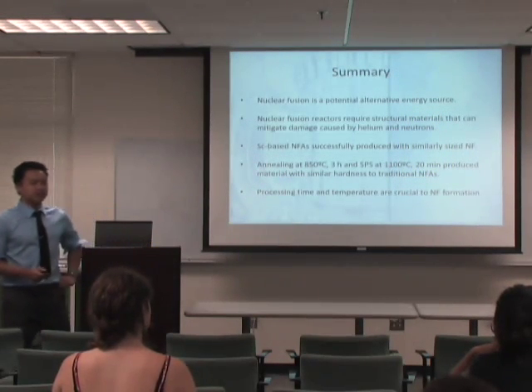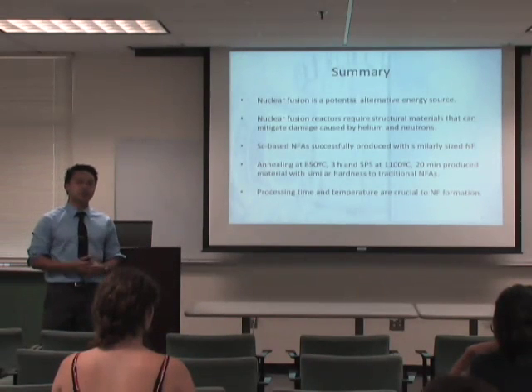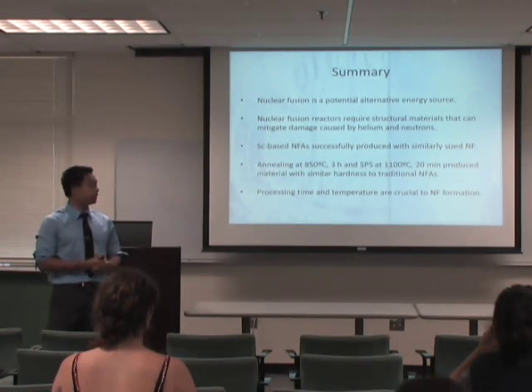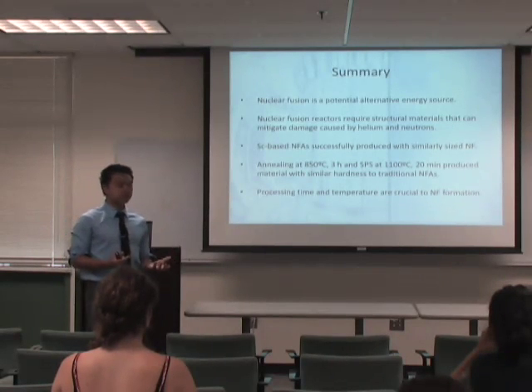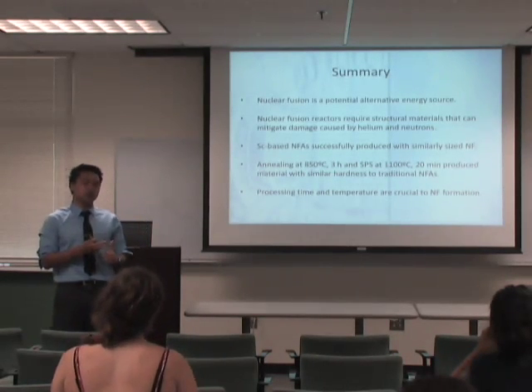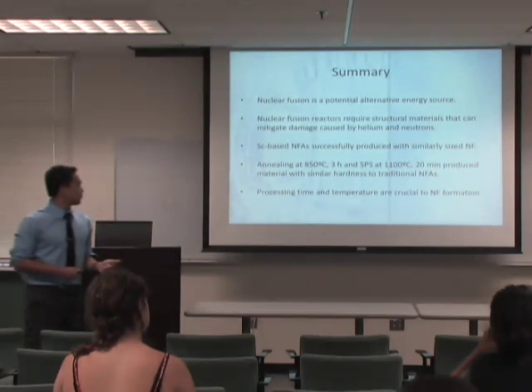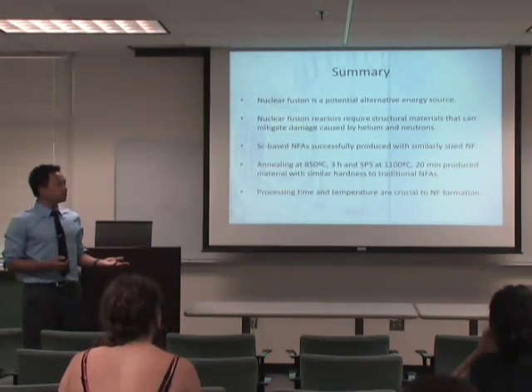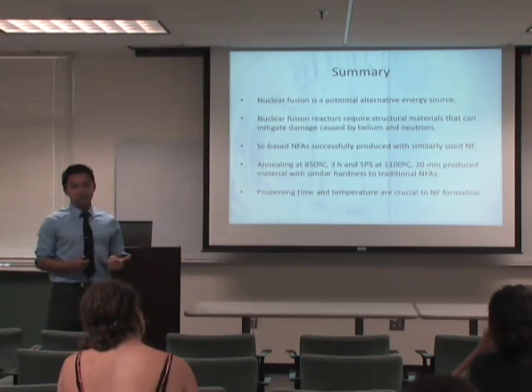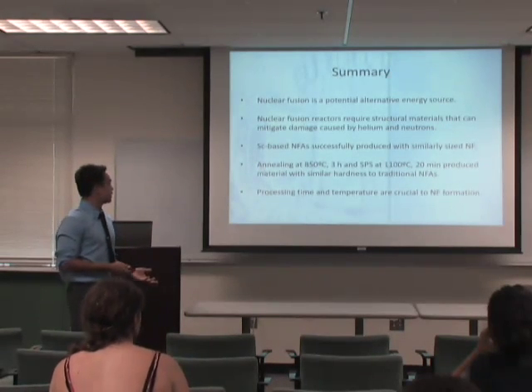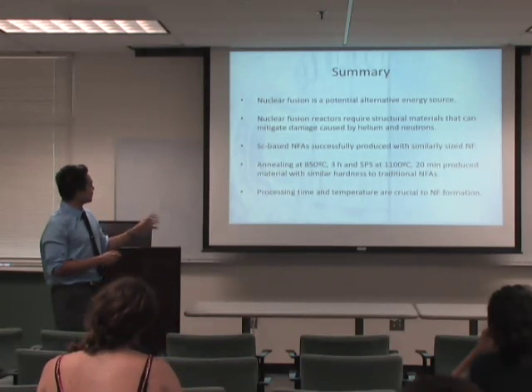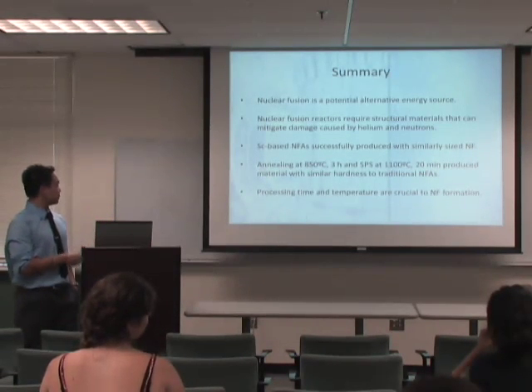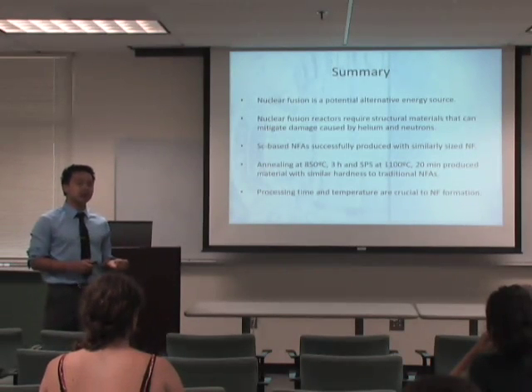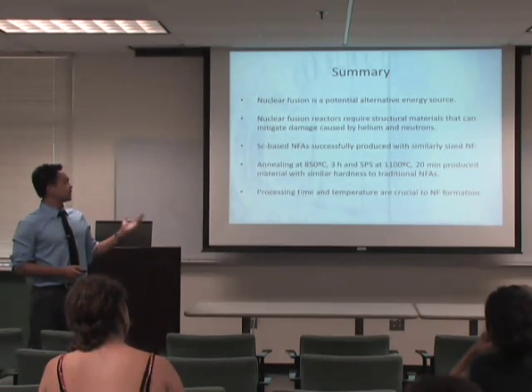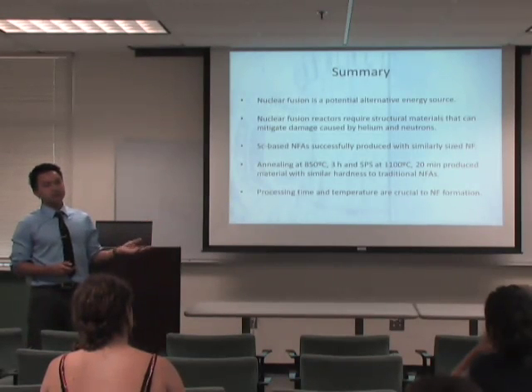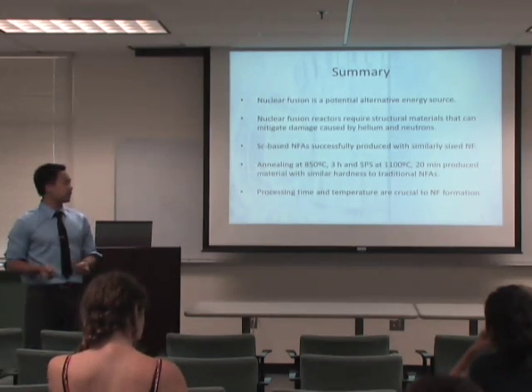So to summarize my talk today, nuclear fusion is a potential alternative energy source. It is green and it is safe. Nuclear fusion reactors require structural materials that are able to mitigate damage due to neutrons and helium. Now my group has successfully produced not one but 2 NFAs that could potentially be used in nuclear fusion reactors. And in my hardness data, I found that my scandium NFAs heat treated at 850 degrees Celsius and my alloy at 1100 degrees Celsius are very comparable with our previous NFAs.